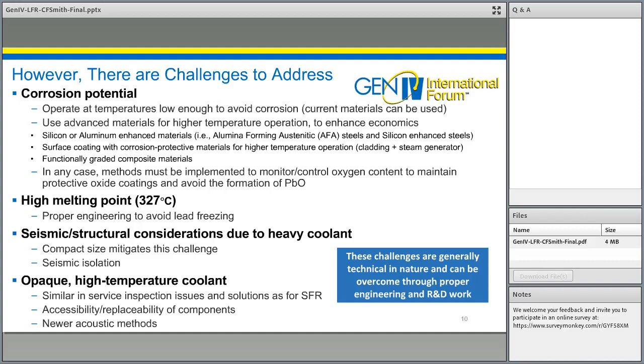A key factor in most designs involves maintaining a metal oxide film on metal structures by controlling the coolant oxygen within a range that is below the concentration for lead oxide formation and above the minimum concentration needed for sustaining a protective oxide coating of the component surfaces. In general, these challenges are technical in nature and can be overcome through proper design, engineering, and R&D. Current reactor designs being considered feature different approaches or even combinations of approaches to corrosion control, and in many cases, the multiple approaches are used depending on which component and what temperature range the reactor is designed to operate in.